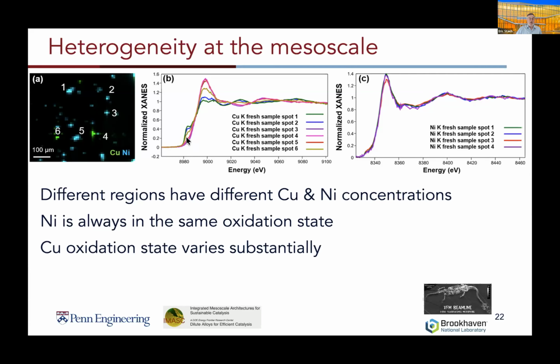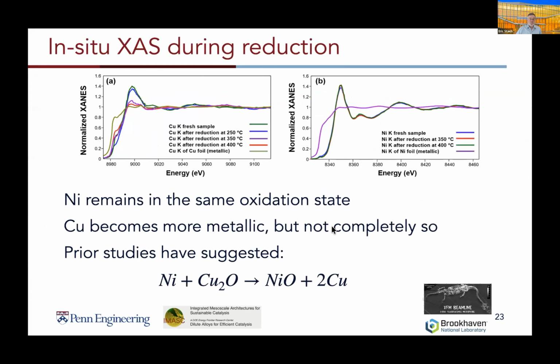And you can see this variety present by looking at the different spots. You're looking at the copper here. This is the K edge, and you see changes in the near edge structure, again, indicating differences in the oxidation state. Whereas again, just like in the EELS, the nickel was more or less the same.